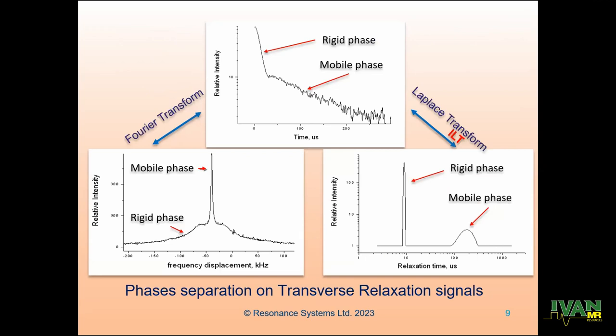So, if we take one of the classical signals, FID or magic sandwich echo, let's say we take a piece of starch or a piece of cellulose and put it into the NMR machine, you will see a decay that, as I already mentioned, can be composed of at least two components. One is decaying fast, which means the faster the decay, the lower the mobility, and it normally decays within 20 up to maximally 50 or 60 microseconds. If you take something rigid, it will decay within this range. And something that decays with a longer curve, longer relaxation, is definitely a more mobile phase.